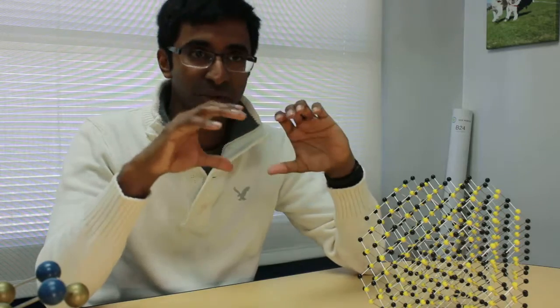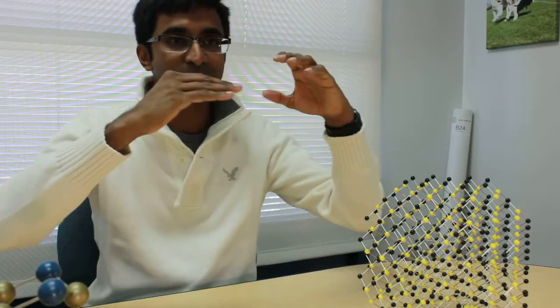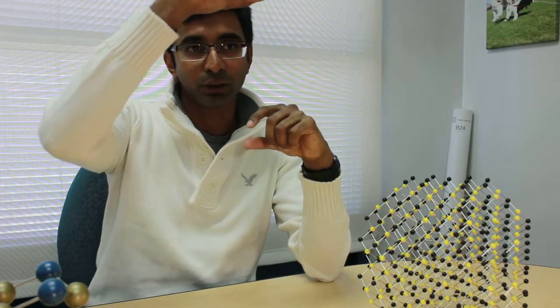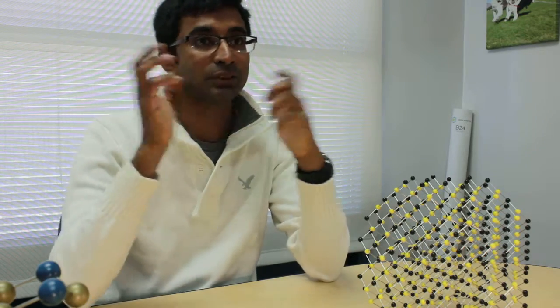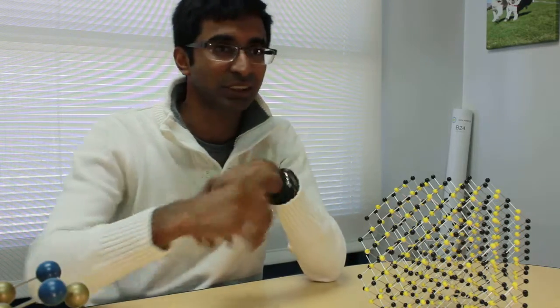And the way these are grown is you grow them upside down on a gallium arsenide wafer, going from the widest band gap grown very close to the substrate and the narrowest gap grown very far away from the substrate. The narrow gaps are typically grown dislocated because they're metamorphic, or you've grown something with a different lattice constant on the substrate, so they are dislocated.